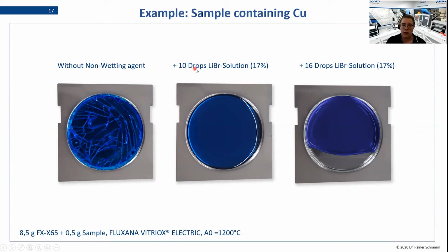Then I did the same sample, same fusion with 10 drops of lithium bromide solution. And we can see here that the bead has a very nice shape. The bead didn't break. And as with everything, there's also a too much. So if we add some more drops of the halogen solution here, we get something that we would call a half moon. So this is too much.